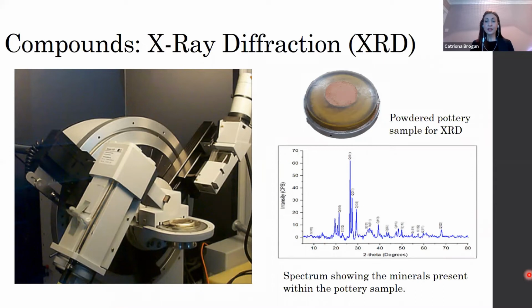So the XRD spectrum has a series of peaks, and each compound normally has a number of peaks. It's represented by several peaks, and these can be identified through their position along the spectrum. So often what we get is, say, this peak relates to quartz, as does this one, as does this one and this one, I think, all with the Qs. So basically, whenever we have a sample that matches up to this, we know that quartz is present within the fabric.